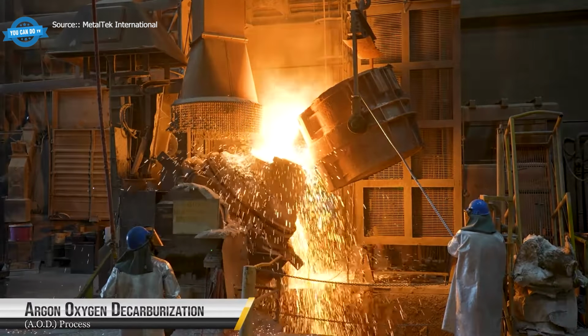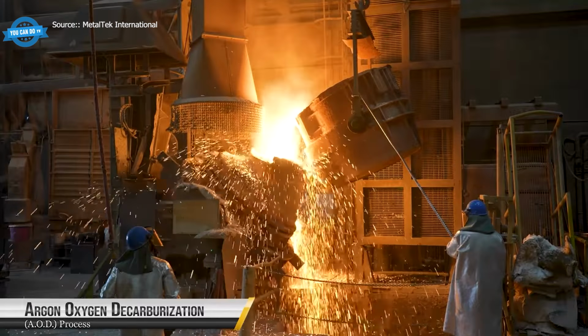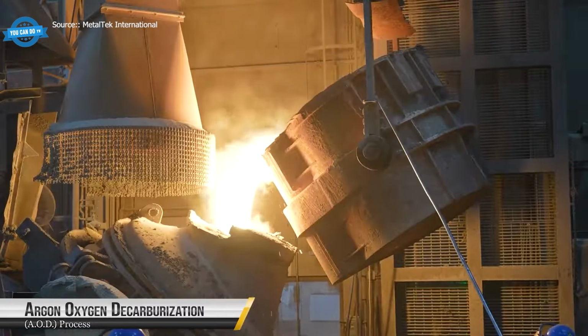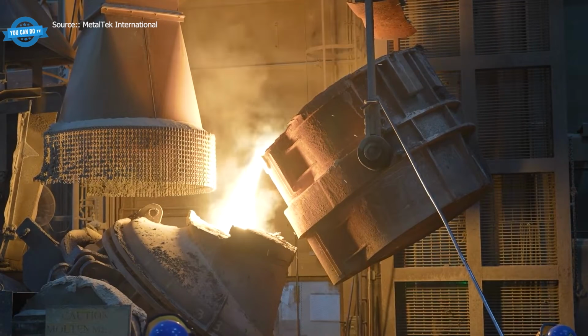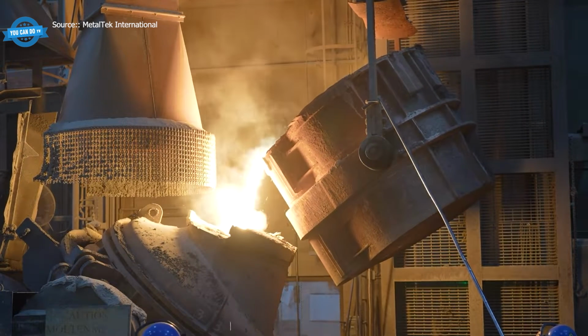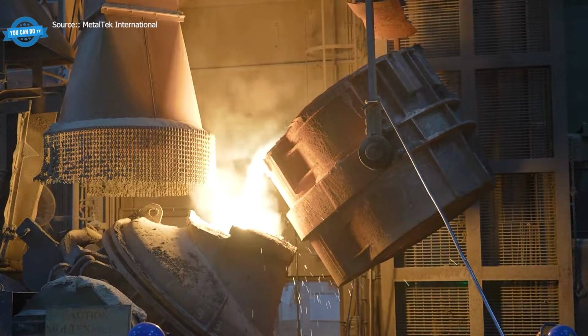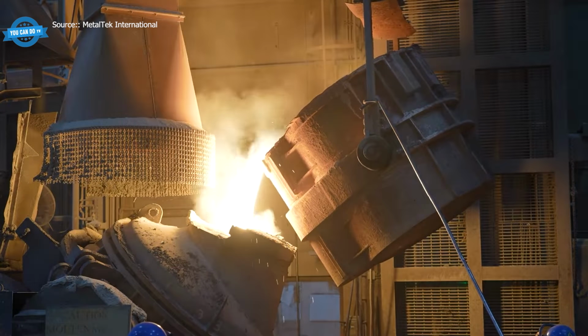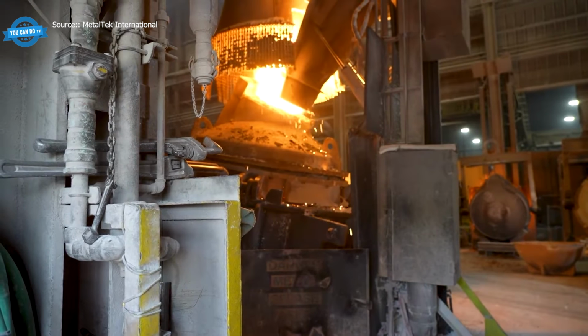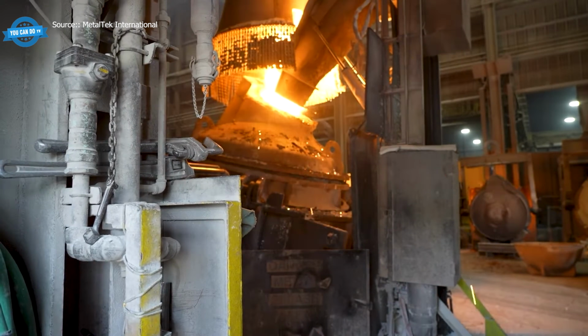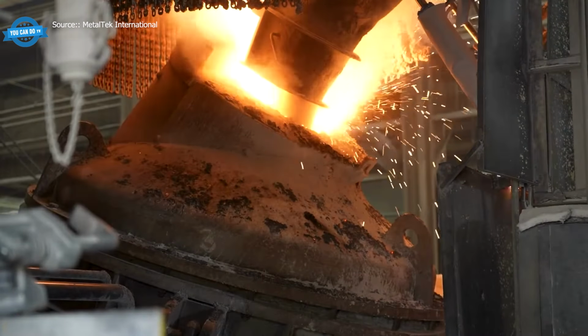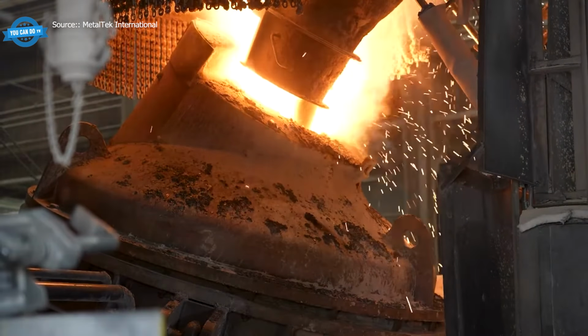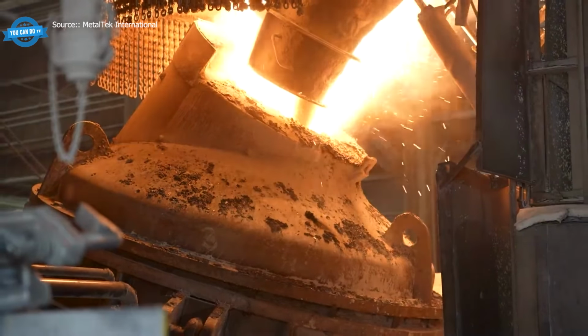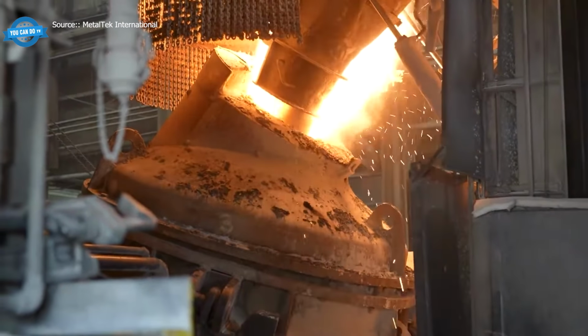Argon-oxygen decarburization, AOD, takes over from there. A mix of oxygen and argon is blown through the molten steel to burn off excess carbon and pull out dissolved gases. Skip AOD, and the steel comes out looking finished, but cracking under actual load. AOD is how stainless steel earns its corrosion resistance and its toughness in one shot.